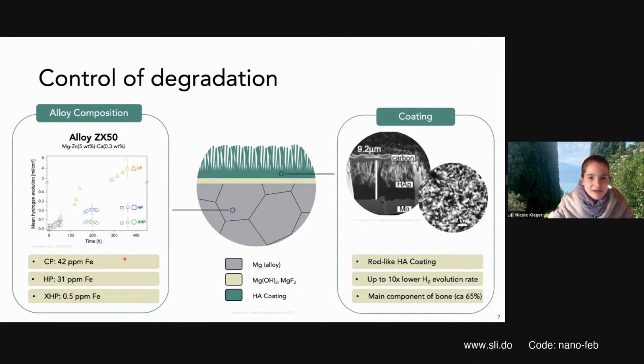Now, the other thing that we can do is coating the magnesium with hydroxyapatite. Now, hydroxyapatite is the main part of our bone, about 65% of it. And we just grow it on top of the magnesium, and by doing so, we can decrease the hydrogen evolution by a factor of 10.